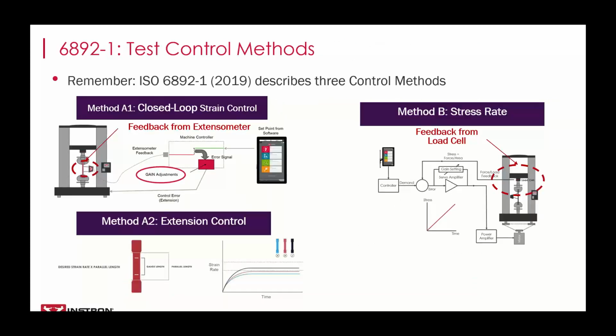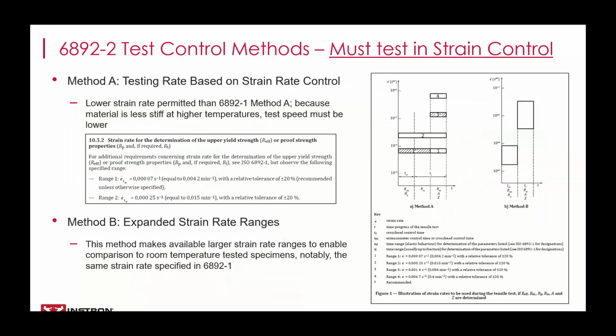So while the normative reference, ISO 6892-1, articulates three valid control methods, that is, controlling by strain rate, stress rate, or extension, ISO 6892-2 instructs that strain rate must be controlled in testing in order to get a conforming result. There are two methods that are provided in the standard. The first is method A, which is most commonly used in elevated temperature testing. This method prescribes a lower strain rate than the normative standard, so the test must be run at a much slower speed to maintain the result.